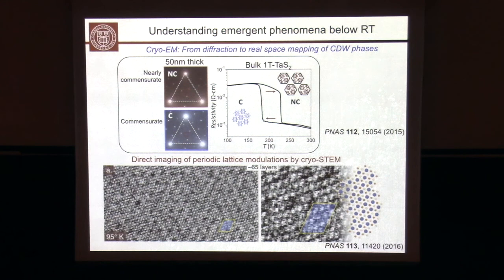Our first attempt was using a microscope without aberration correction, just to demonstrate we're sensitive to those lattice distortions. This picture is a thick sample, 65 layers, so that's quite thick. This was our first experiment at liquid nitrogen temperature. We already see a superlattice structure. These are the dark spots. The tiny spots, those are the atomic columns. But the dark spots encode exactly this commensurate state in 1T tantalum disulfide. So yes, we are sensitive to it, but we cannot extract quantitative numbers for that. In order to do this, we need to go to aberration corrected tools, and I'll show you where we have come with this in a minute.